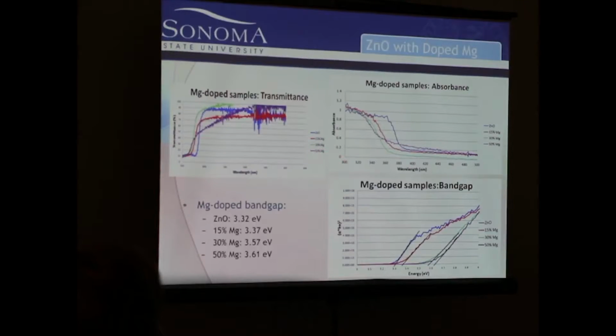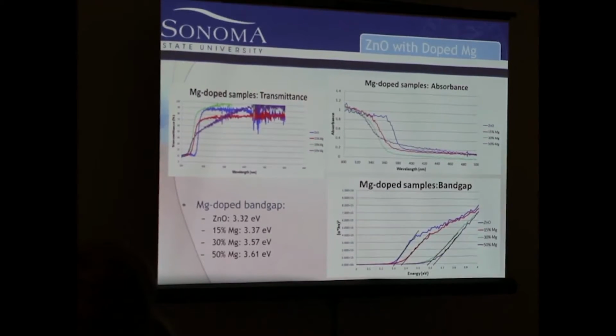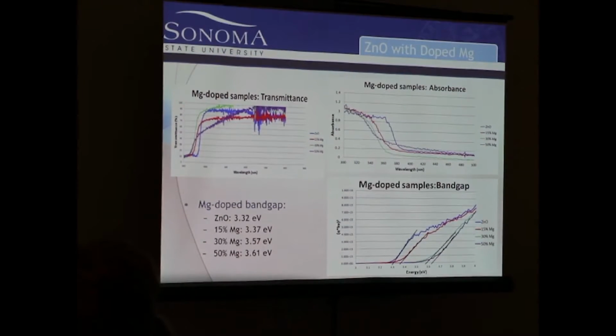And then 30% was oddly a little higher, and that could be due to various annealing temperatures, because that dissolves some of the unwanted solvents, so we have more zinc oxide. So that could have been something that changed. And then at about 50%, we get about 40% transparency, which is not desirable. It's not something we want, but that is what we got, and so we know that above 50% is a little too much for magnesium. We also check the absorbance, and that's a key component because we want the UV light to be absorbed, anywhere from 250 to 400 nanometers on the light spectrum. Our zinc oxide gives us this nice little slope and fairly flat to zero after about 400, which is something that we're looking for. So that's just our starting point.